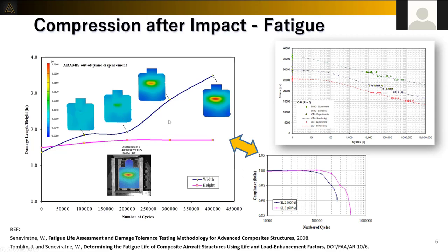So what you can do is use ARAMIS. Here, what we've done is use the ARAMIS digital image correlation images, and really understand the progressive damage growth and how it affects the rest of the coupon. For example, here you see the stiffness reduction in this coupon. I believe this is the magenta line, and you can see, as the damage grows, my compliance changes. So in this case, my stiffness starts reducing. But at this stiffness reduction, now we can correlate to a certain damage configuration in this coupon.